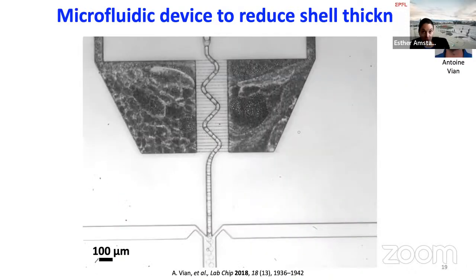The other method, which is a little bit more of an engineering approach, is that you minimize or reduce the number of drops that form within these oil shells through the dimensions of these double emulsions. For these small drops to form, you need some sort of convective flow. And if you increase the hydrodynamic resistance within the capsule shell by making this shell much thinner, you reduce the convective flow within it. And the hypothesis was that then you slow down this transport.